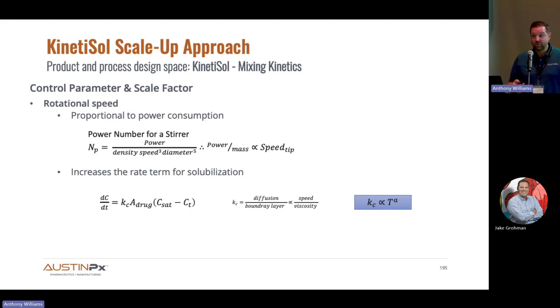And one of the best ways to make those go away is with shear. So we've got this high shear mixer, and we can make that boundary layer go to almost nothing. In fact, I would argue a lot of the crystals fracture and the area goes up, but really the temperature also affects this, and so does the RPM. So we have 2 different parameters. Both of them make the dissolution rate go faster.